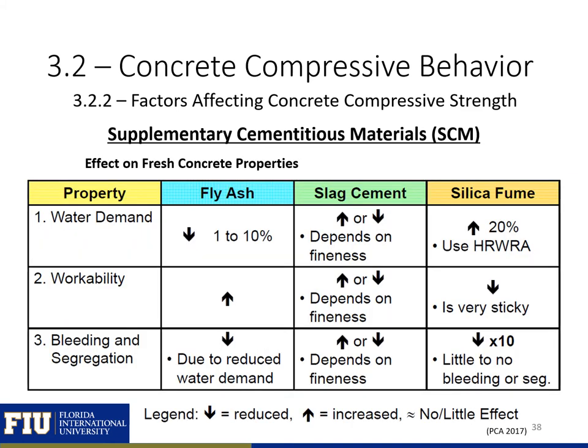The next slides show how these three SCMs impact the fresh concrete properties and the hardened concrete properties. Fly ash will generally decrease the water demand slightly. It'll improve the workability due to the ball bearing effect of the spherical fly ash particles, and it'll decrease the bleeding and segregation. The impact of slag cement on the water demand, workability, and bleeding and segregation is dependent on its fineness. Silica fume will dramatically increase the water demand. It'll decrease the workability, and it will decrease the bleeding and segregation.